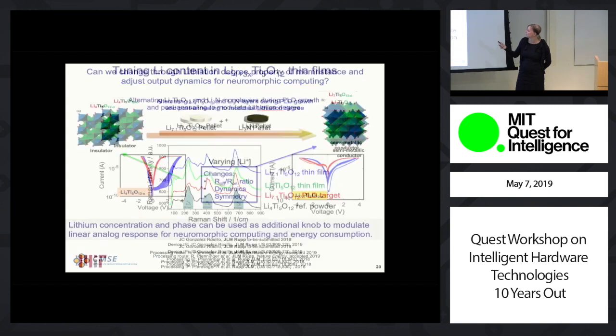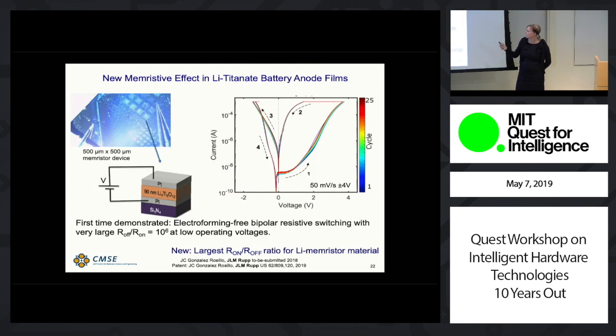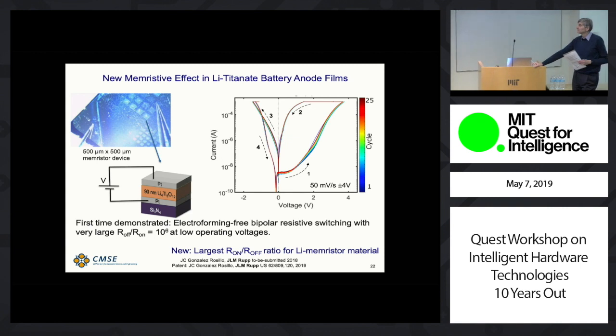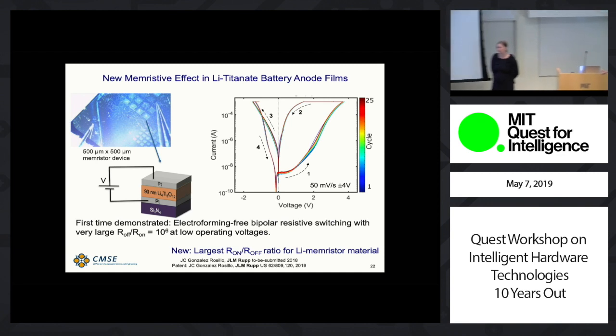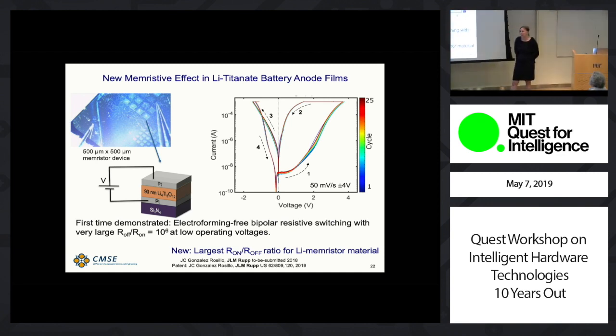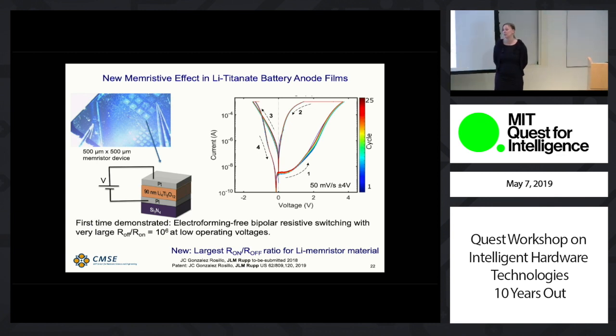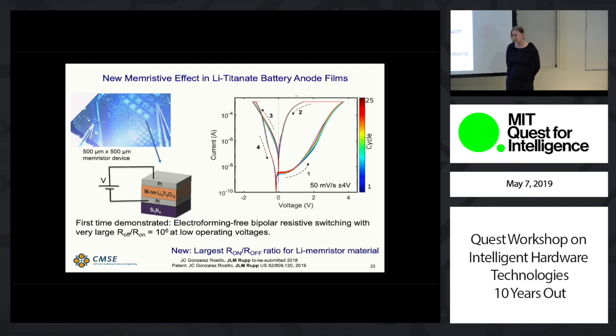Going back to the result, for all of those you can run it, and it's a very low scatter for the Memristor. They run quite stable over several cycles. Cycling stability is fine, but when you remove the voltage, how can it not go back? I don't understand. I think you have to think of it as an order of magnitude increased conductivity and diffusivity compared to other oxygen ion conductors. But those would also not immediately swing back just because they are bipolar two-terminal devices. Let me suggest we take some more questions.